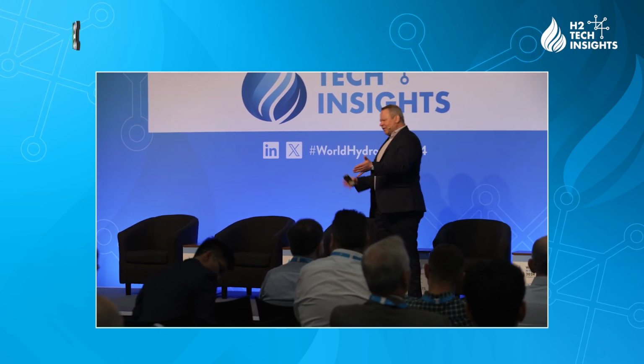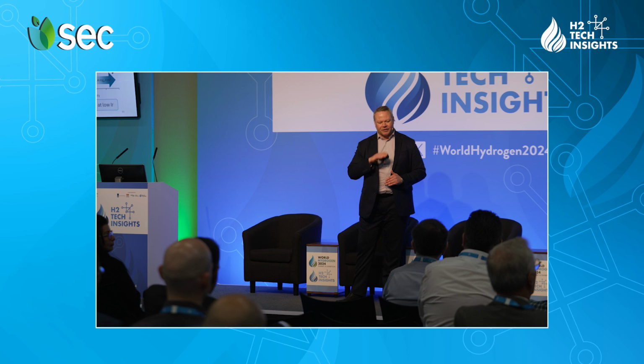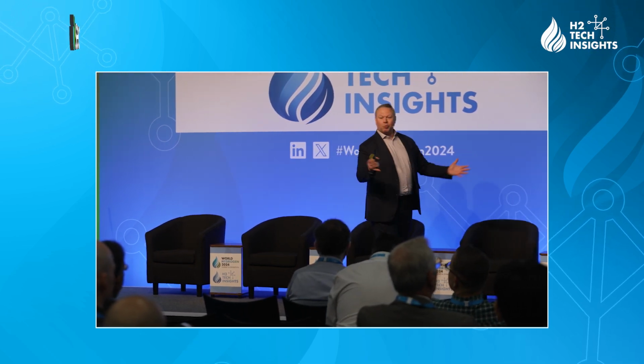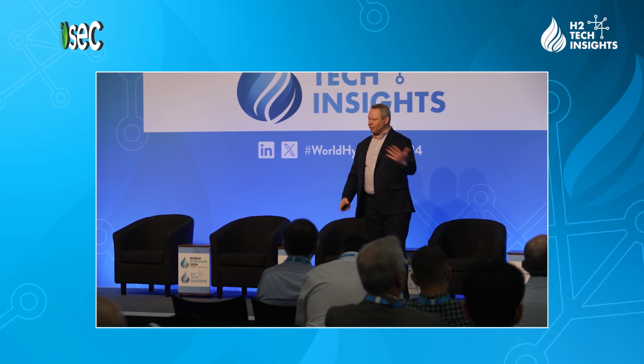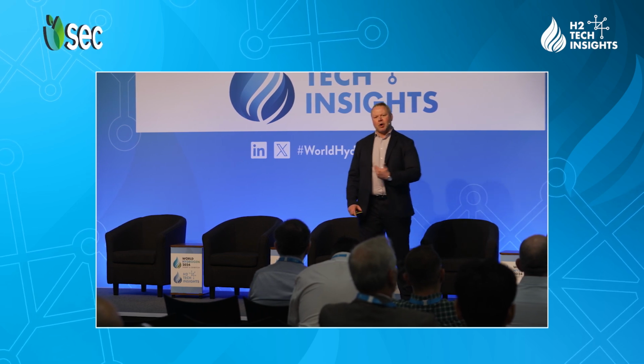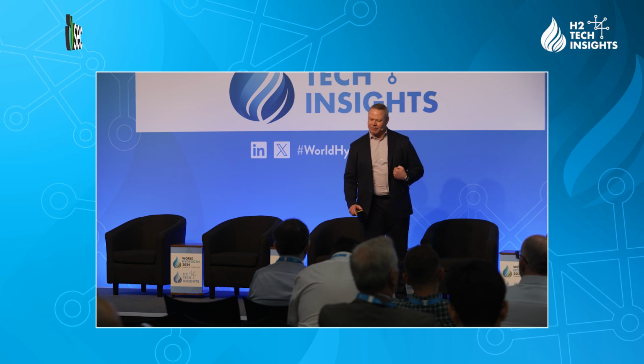What you see here is sort of evidence of that, and I'm being glib, but at 0.4 milligrams per centimeter squared, there's virtually no dependence of either the cell voltage or the high frequency resistance on porosity. But as soon as we drop down to that aggressive 0.1 milligram per centimeter squared loading, all of a sudden we see this very sharp correlation between loading, porosity, and performance. This is extremely interesting. What this tells us is that we should actually be striving to make the porosity of our PTLs lower to reap the benefits of ultra-low loaded CCMs.